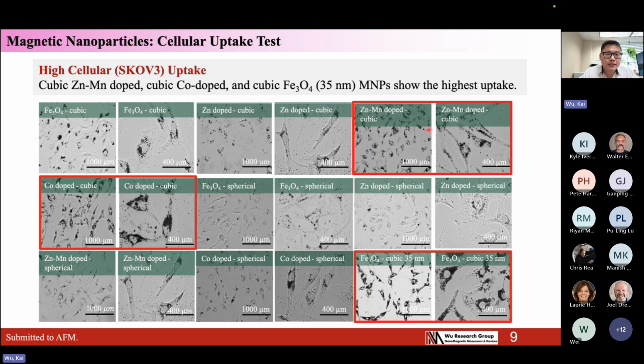And among all these images, you can see that some particles, like the Fe3O4 cubic nanoparticle, show some uptake of MNPs inside the tumor cell. You can see from the boundaries of the cell membrane. In all the figures, you can see a very light color of the boundary of the cell membrane, and you can see the particles, the darker color, accumulating inside the tumor cells. Which shows you that all the particles have some varying level of cellular uptake.